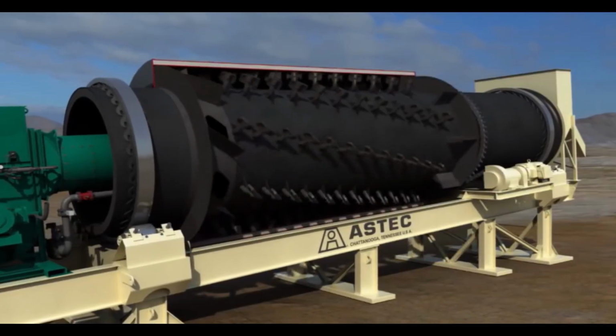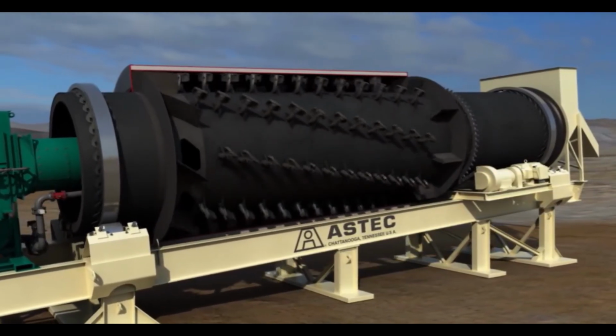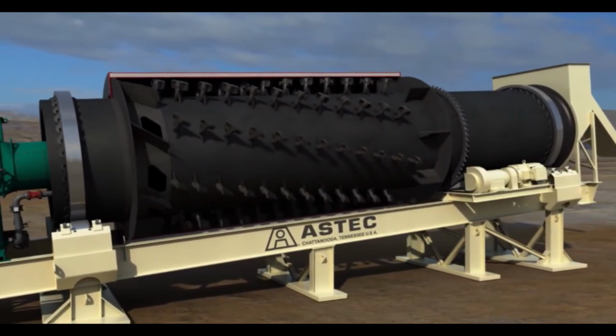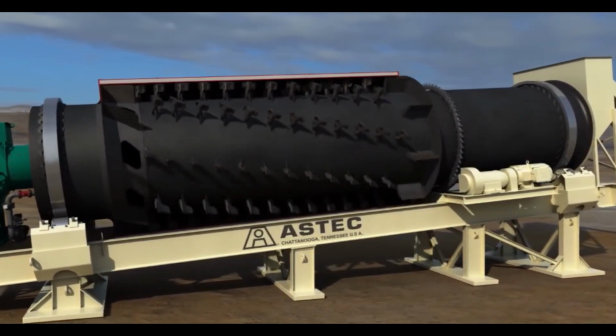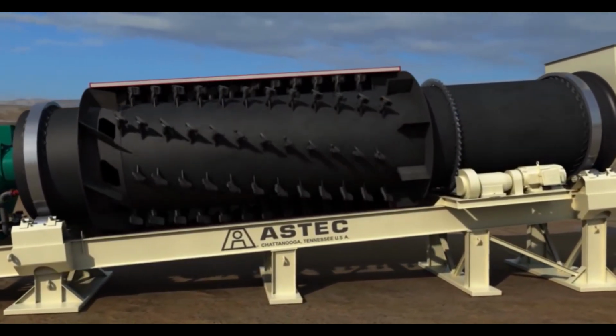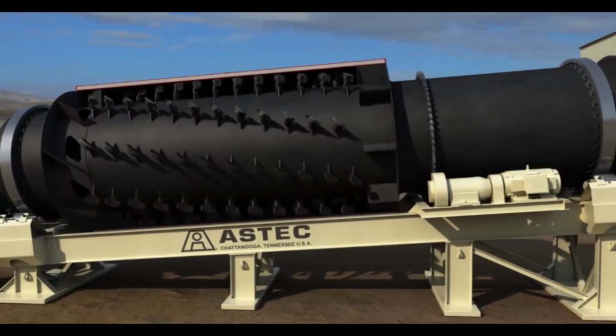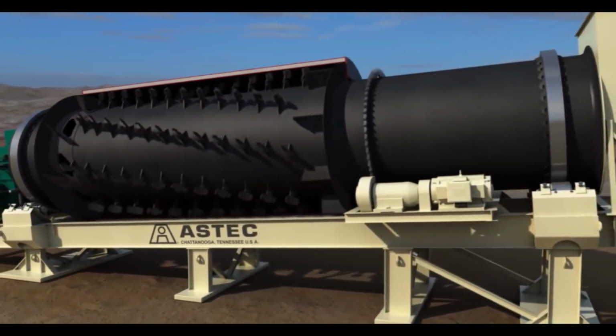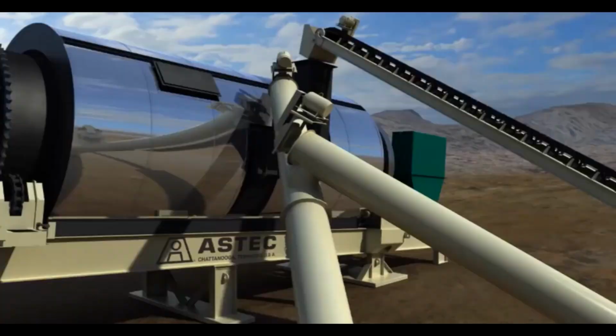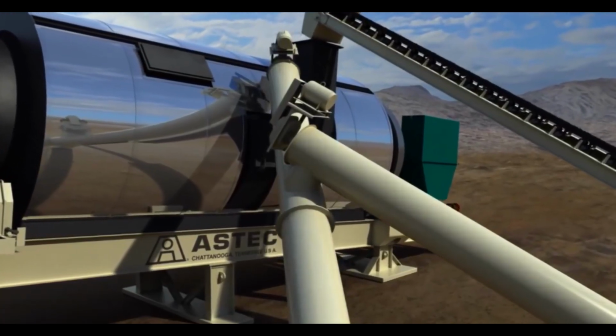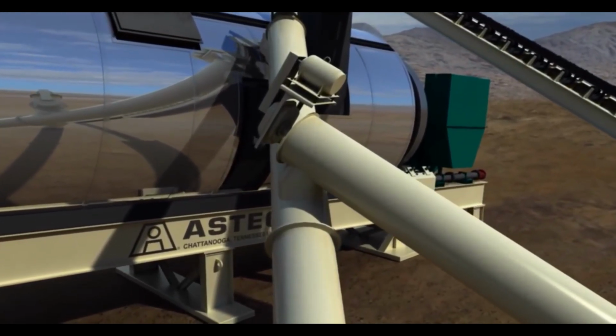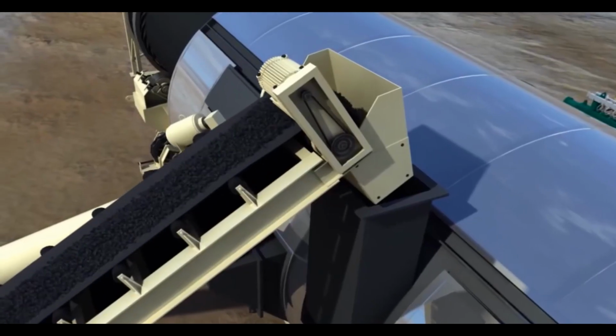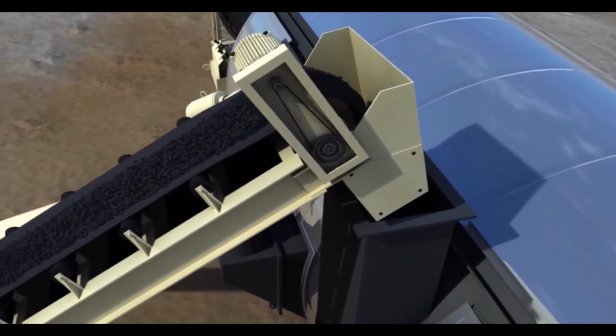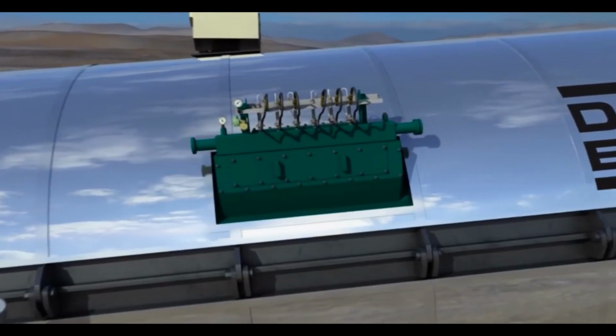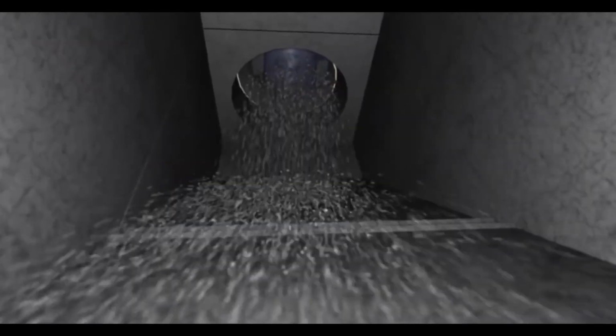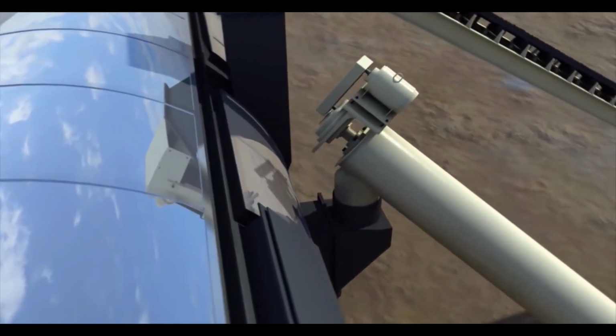The insulated outer drum provides a long mixing chamber where mix ingredients are added to the hot, dry aggregate in an order that allows better temperature equalization and more even distribution of all particles throughout the mix. The double barrel utilizes a sequential mixing order. First, hydrated lime is added when required by spec or mix design, followed by recycled asphalt pavement, known as RAP. Then, liquid asphalt cement, or AC, baghouse fines, and finally, dry additives.